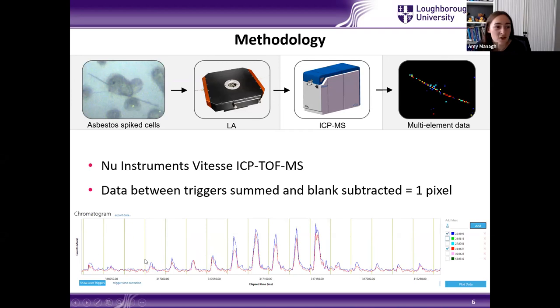And you can see that at 50 hertz, our peaks are resolved from each other. We were getting about 10 millisecond washouts within this data. You can also see in green here, we've got some vertical lines coming down. These were the trigger signals that we got. So every time the laser fired, we sent a trigger signal to our mass spectrometer. And when we came to do the data processing, we summed between each of these trigger signals to give us one pixel in our final image. So as I said, every laser shot is one peak, and then every peak was converted into a pixel in the final image.